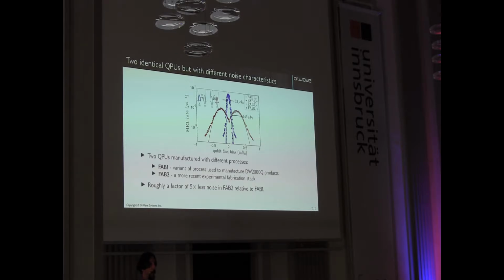So if you're typically looking at gate model systems, often you have those controls where you're pumping the system between ground and first excited state, often with resonant excitation. In D-Wave processors, we have very tight bandwidth limits on all our bias lines because we're trying to limit the amount of noise that's going down from the external environment at 300 Kelvin and reaching the mixing chamber. So we end up having to look at our systems where the dynamics are relatively slow. So this pushes us out into the incoherent tunneling regime. But nonetheless, it's a useful measure.